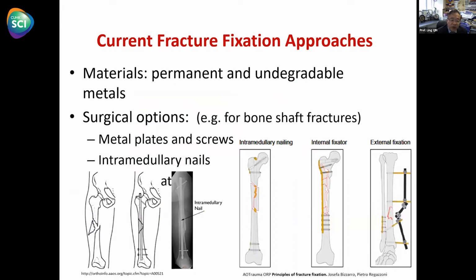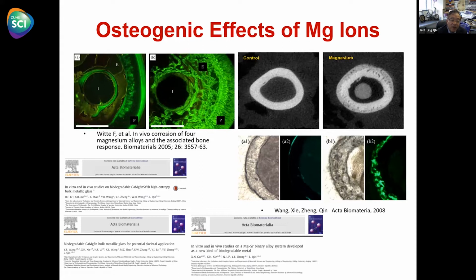Traditionally with permanent metal, as you can see here, there are different approaches. We tested biodegradable metal compared with polymer. Nowadays, polymer is quite inert; after two years, there is even no degradation. It used to be designed for degradation, but too fast. And you see here biodegradable magnesium stimulates a lot of bone formation, as reported by others. This is our own data: you see the magnesium implant here, and many bone formations using labeling, showing those are new bones.